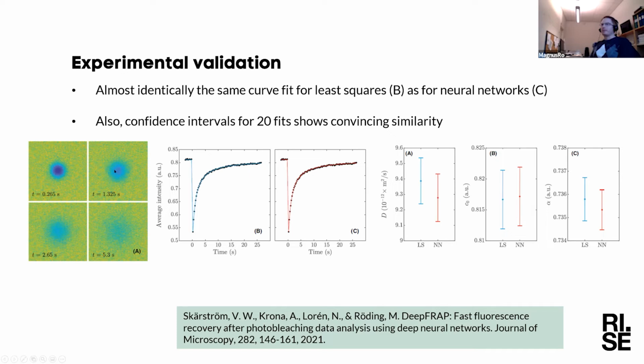We have real experimental data here that we evaluated on. And if you see here, the least squares fit with a conventional numerical method, and the curve based on the predicted parameters from the ANN, are virtually indistinguishable. And if we do that with 20 replicates, this is 20 real experiments, we get a slight difference in these confidence intervals for the 3 predicted parameters, but the difference is very small and not statistically significant. So we get something which is orders of magnitude faster, with essentially the same performance as the least squares.